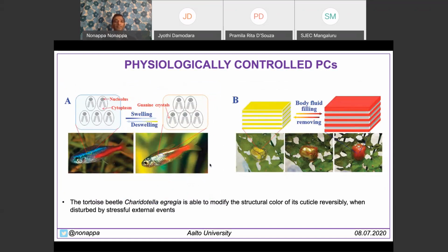Another interesting example that we can see is in the fish and beetles. And these are examples of physiologically controlled color. It has to do with a well-ordered structure, but it's not a permanent structure. Depending on the environment, the animals can excrete certain body fluid that will modulate the color, essentially the refractive index. And in both cases, in the fish and beetle, you have a layer of guanine crystals, the molecular level building block, which forms nice microcrystals, and alternating layers of guanine crystal and cytoplasm.